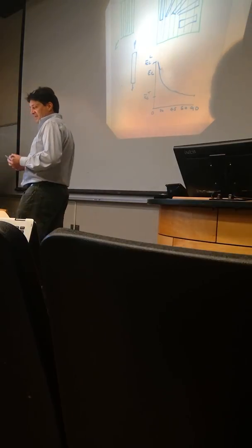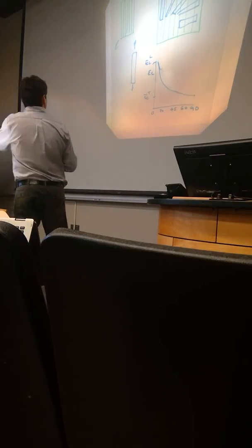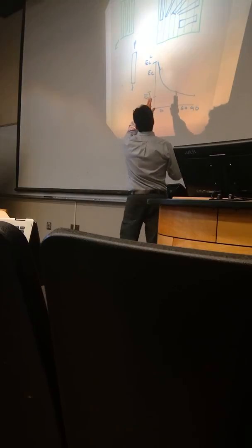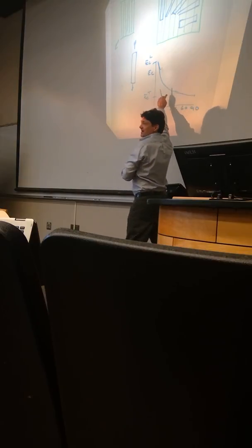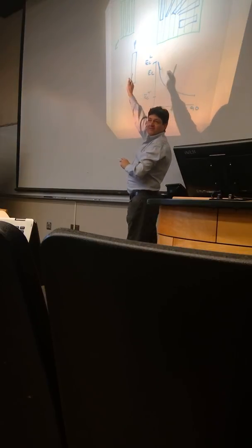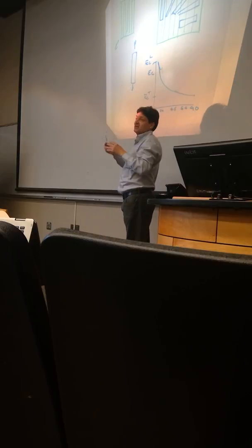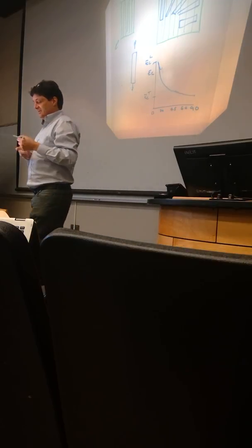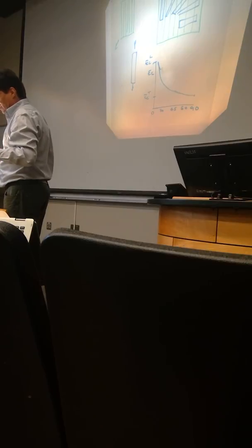This would give you E of the composite transverse. At 0, it would be E of the composite longitudinal, and let's see, 30, 45, and 60. So you get a pretty fast drop off. At 45 degrees, E of the composite is not half of what it is. It's about a third of it in the other direction. So it's a nonlinear relationship there, and it drops off pretty quickly.